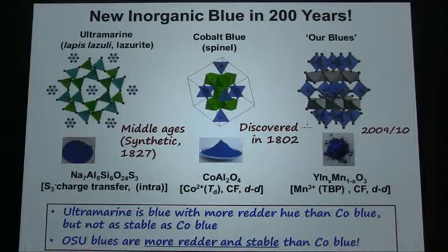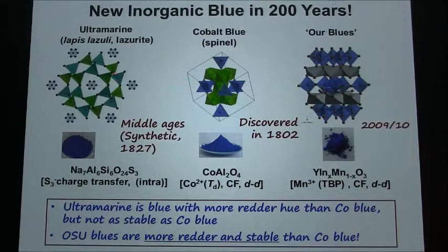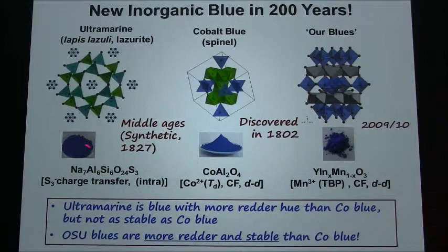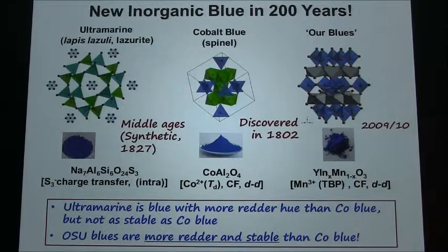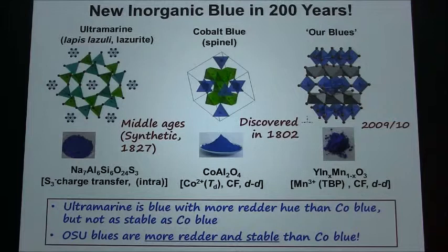This blue color is very vivid, and it's pretty much as good as ultramarine, but ultramarine is very unstable. That's why you can't use ultramarine outdoors. You have to paint only indoors, because any touch of acidic solutions, like acid rain, can completely change the color to white. But our pigments are highly durable. You make them at very high temperature, as you can see, so they cannot be easily faded. That's why it has become a very popular blue pigment discovered in recent years.